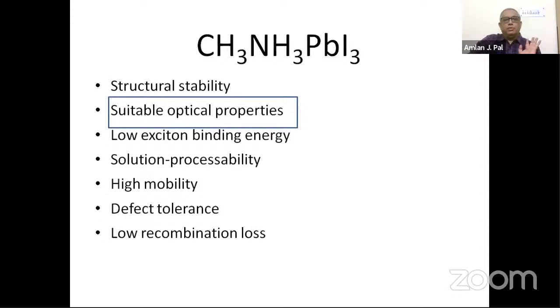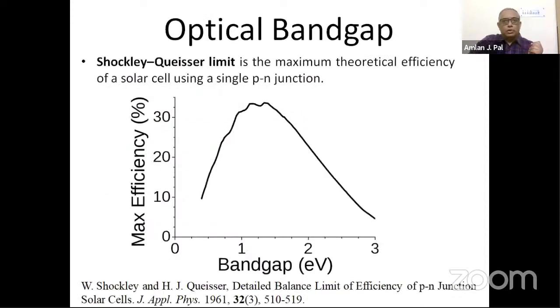And its optical properties are beautiful. The first thing for those who work on solar cells is that they start with the Shockley-Queisser limit. That is the theoretically predicted value, the maximum efficiency that you can get from a single p-n junction, which depends on the material's band gap. It is a very old paper, from 1961. So that is the reason you try to get materials with a band gap of about 1.23, like silicon, because it has the possibility of the highest value. If you try a material at 2.5, you know you can never get more than 10% efficiency. So that is what we call the Shockley-Queisser limit. So where do our perovskites stand?